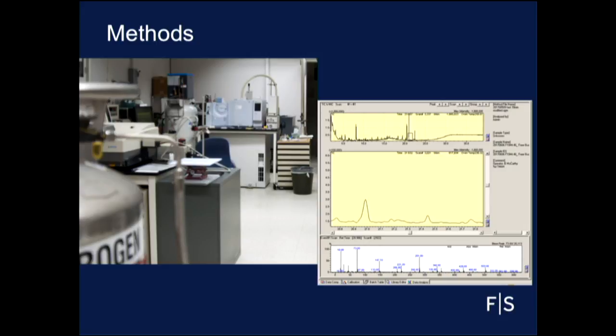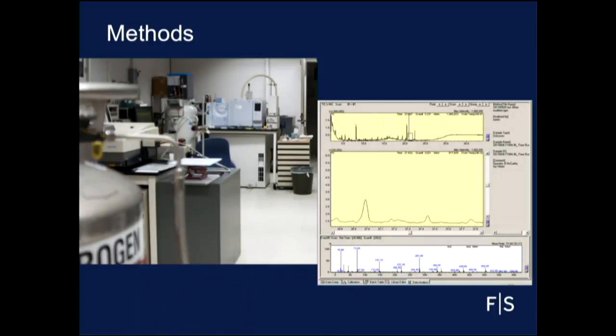This helped us to identify the components in each of the lacquer layers. Now, the stains that we applied during microscopy did help us to localize some of the materials that were identified by GCMS. Where it worked, this was helpful, as some of the layers of the lacquer were too thin to allow us to get GCMS results from a single layer. Overall, however, the stains were of only limited utility, as many of them stained black. And these lacquers are black on black on black on black.